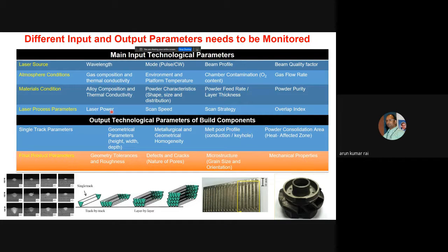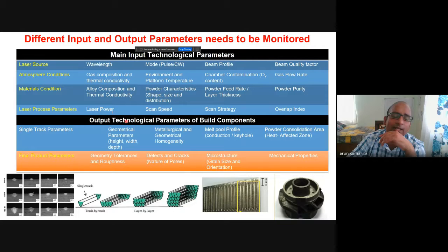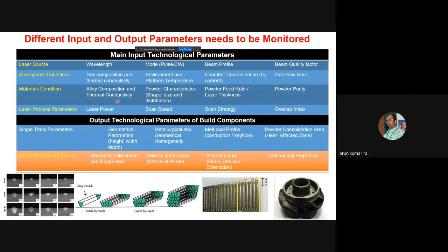So I can melt a ceramic with 250, 300 watts of power, but with the same power, I cannot melt a steel, because steel is iron based, it is metal based. So in metal the reflectivity is 60%, only 40% absorption is there. So with the same power I cannot melt. So this laser power has to be decided as per the melting temperature as well as the reflectivity and absorption of the material. So this is the one.